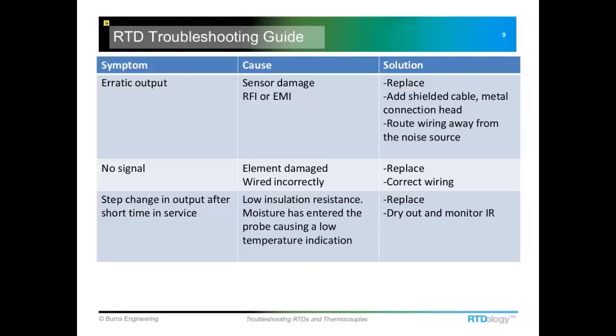circuit. The only solution to that, of course, is just to replace the probe and maybe look at one that might be a little more durable, or perhaps even reposition the sensor to a different location where it's farther away from shock or vibration. One of the common places for mechanical shock to happen and damage a sensor might be in a pipeline that has a steam injector right just upstream of the temperature probe. And when that steam shoots into the pipe to heat up the product, that can cause a little bit of a water hammer, and that's going to destroy an RTD in a very short amount of time. Those little platinum wires and lead wires and things just can't survive that much abuse.